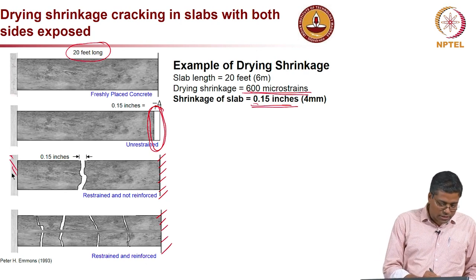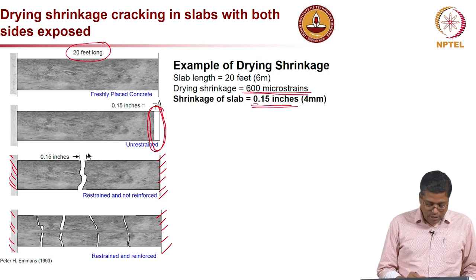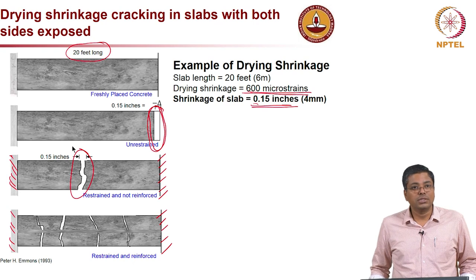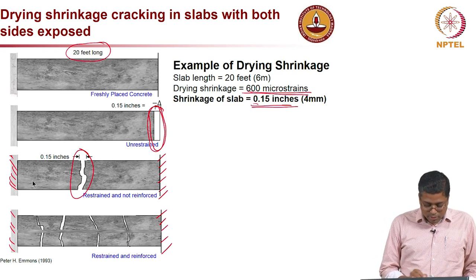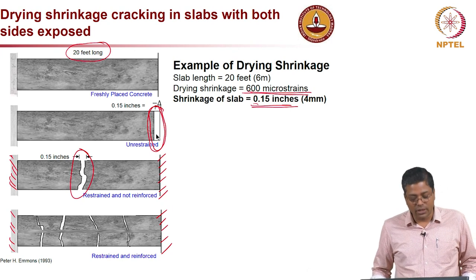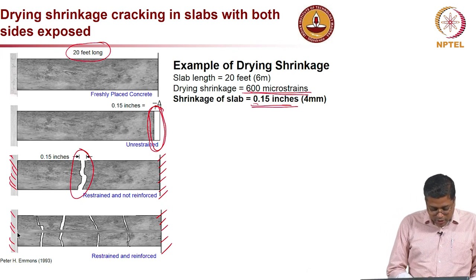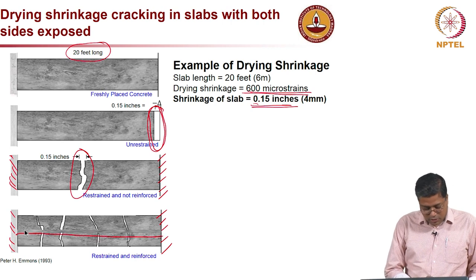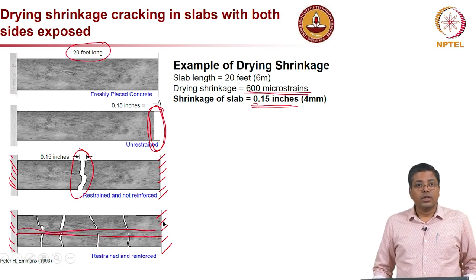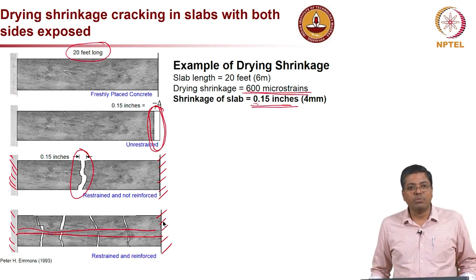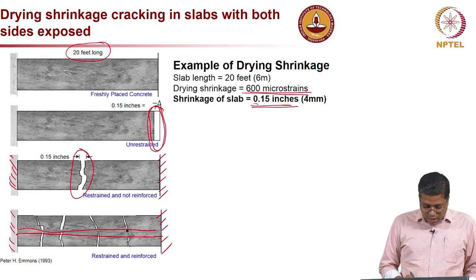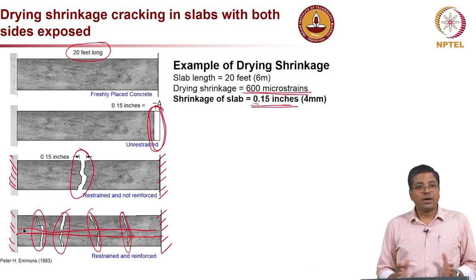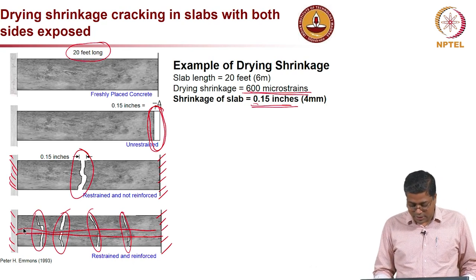But if both sides of the concrete are restrained or held, then the crack will form almost at the center, okay. So it is the same crack width, but one crack will form at the center. Now if you provide reinforcement, as you see in this picture, there is a rebar going through the center. That provides an additional restraint, and that will lead to multiple cracks. Like in this picture you see 4 cracks, but the crack width of each of them is relatively less than the 0.15 inch or 4 millimeter crack, okay.